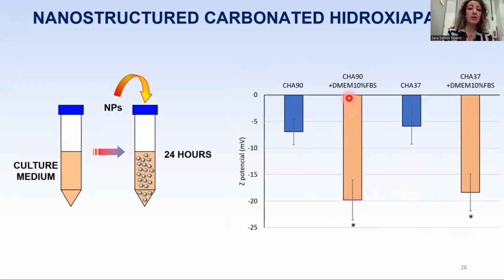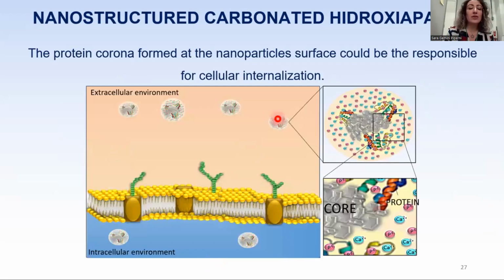This is shown in this graph because the Z potential decreases a lot when the hydroxyapatite is in contact with the medium for 24 hours. So this demonstrates ion adsorption. And this characterization is very important to hypothesize that a protein corona formed at the nanoparticle surface could be responsible for cellular internalization as a Trojan horse-like mechanism. It's the same that we observed in the titanium dioxide. So this mechanism hides the particle in a layer that is constituted by fetal bovine serum components and ions.